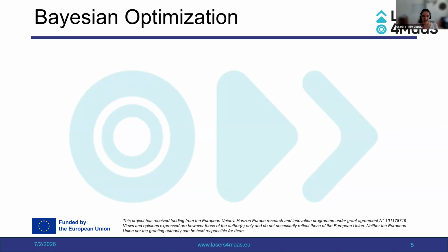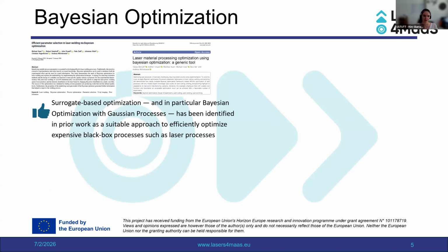I'll show you now. We're using Bayesian optimization. Colleagues of mine and probably quite a lot of other groups now showed and thereby demonstrated that surrogate-based optimization, and in particular Bayesian optimization with Gaussian processes, are really good for identifying process parameters in order to fulfill predefined targets and to efficiently optimize black box processes, so where we don't know the exact behavior.